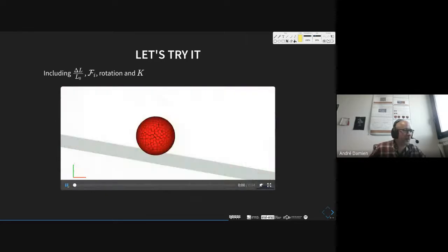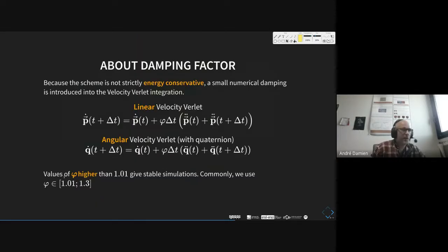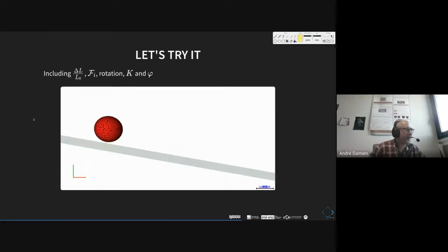So we need, I think, a last ingredient, which is a small damping factor, because in fact, this scheme is not strictly energy conservative, and I chose to introduce a small numerical damping factor in the velocity Verlet scheme. The initial velocity Verlet scheme is a centered integration scheme. So in fact, this is now a decentered integration scheme, and it introduces a very small numerical damping factor, and it is able now to stabilize the simulation, as you can see here. And here it works, I have to say.